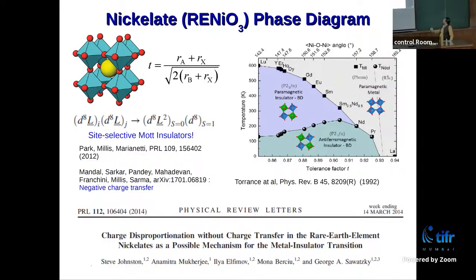You just asked about the bond length. Indeed, that gives rise to a bond contraction and expansion, like a breathing distortion in the entire lattice, which is also a signature of a charge density wave. So it's a charge density wave, but that charge density wave is in terms of the ligand, not in terms of nickel; the nickel electron doesn't do anything. That's the point. There are a few papers from the experts in this field, like Sawatzky, Millis, and others, and there are actually experimental signatures of it.